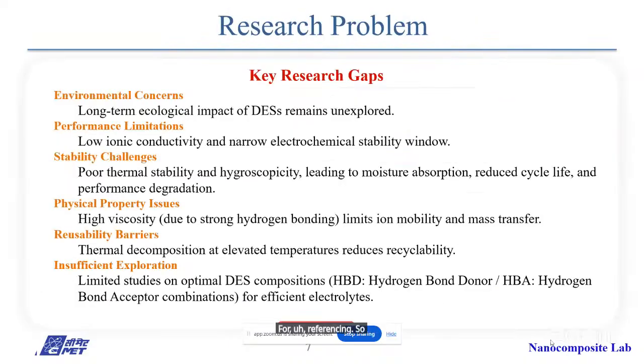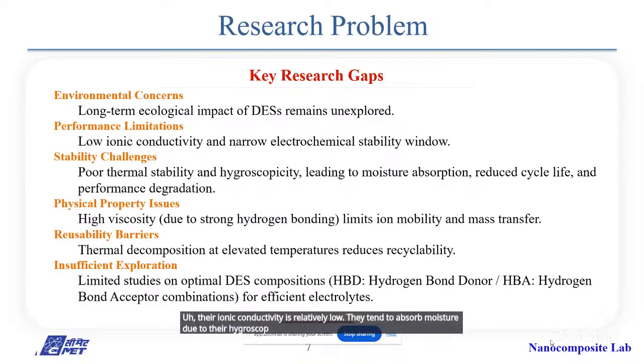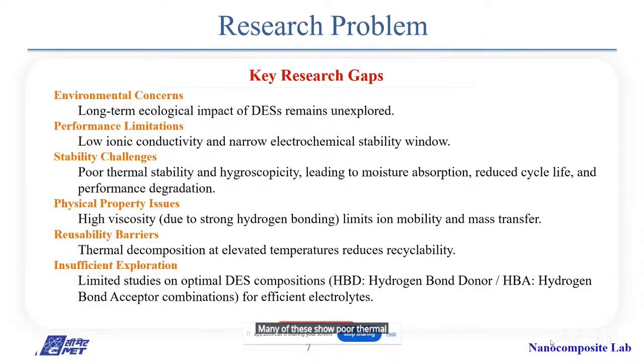So there are research problems which I have found. Despite the potential of DESs, there are some significant challenges that my research addresses. Their ionic conductivity is relatively low. They tend to absorb moisture due to their hygroscopic nature. High viscosity hampers lithium-ion mobility. Many DESs show poor thermal stability and are hard to recycle. Also, very few studies have systematically optimized the HBD-HBA combination for battery applications. Hence, there is a clear gap in exploring DES composition tailored for high-performance electrolytes.